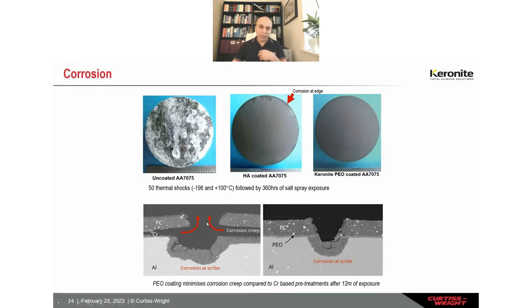In the bottom picture here we have a powder coated aluminum substrate. On the left one, you have the chromic acid anodizing treatment first. On the right-hand side, you have a thin layer of PEO. What has been done here is the powder coat was deliberately damaged, scratched, and exposed for 12 months to salt spray solution. What you see on the left-hand side is typical, what we call corrosion creep.